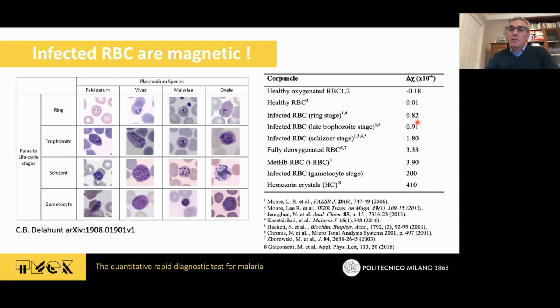It's a very low susceptibility, but still there. When you move to the schizont stage, which is that immediately before the rupture of the cell membrane, it is 1.8 × 10^-6. And if you completely oxidize and turn the hemoglobin into methemoglobin, which is something that we are also using in our development for producing a red blood cell which mimics the infected one that we can produce in the laboratory, you get 3.9 × 10^-6.